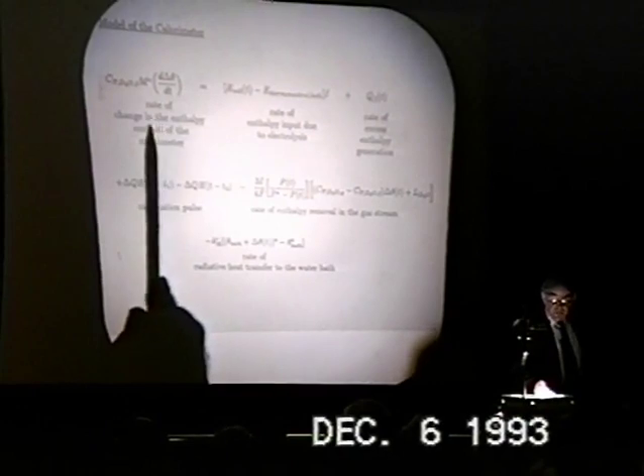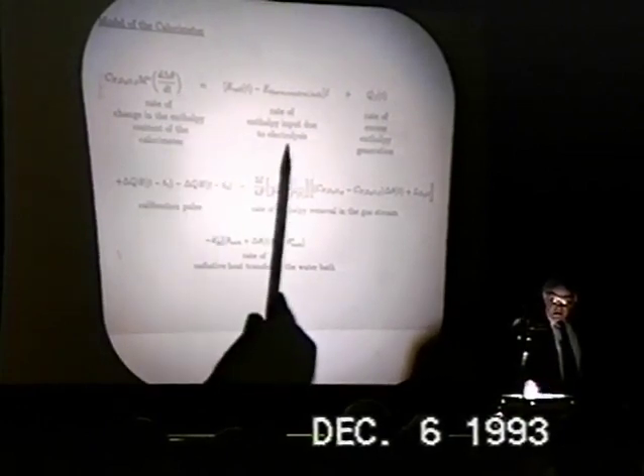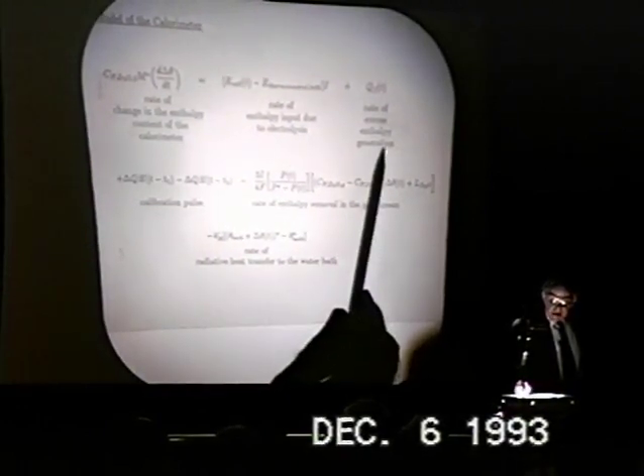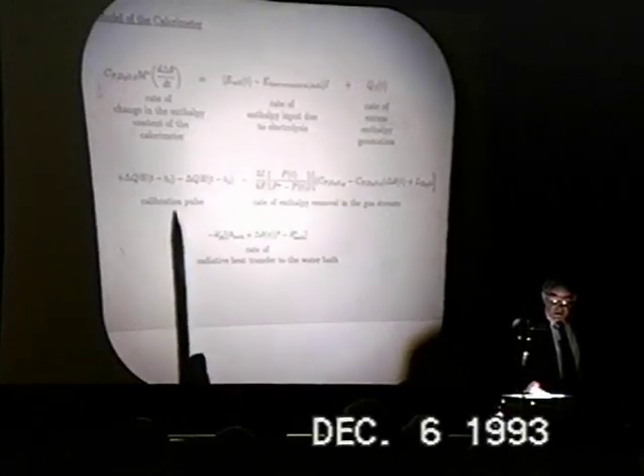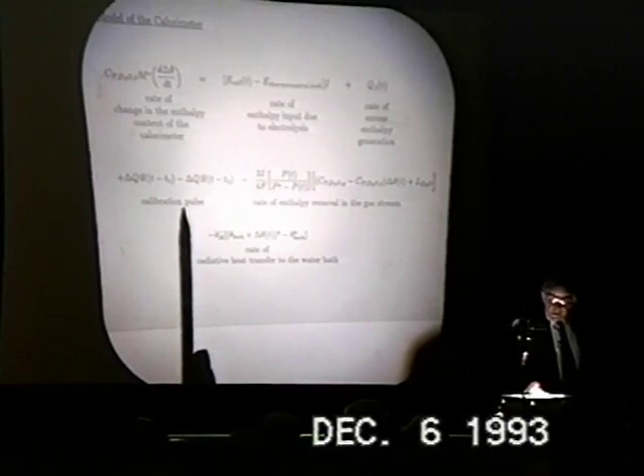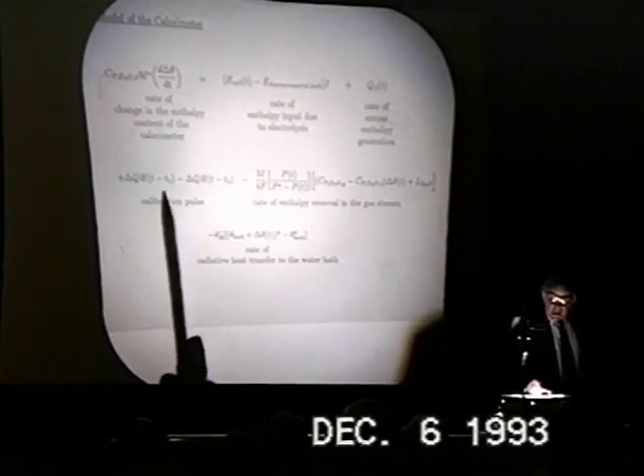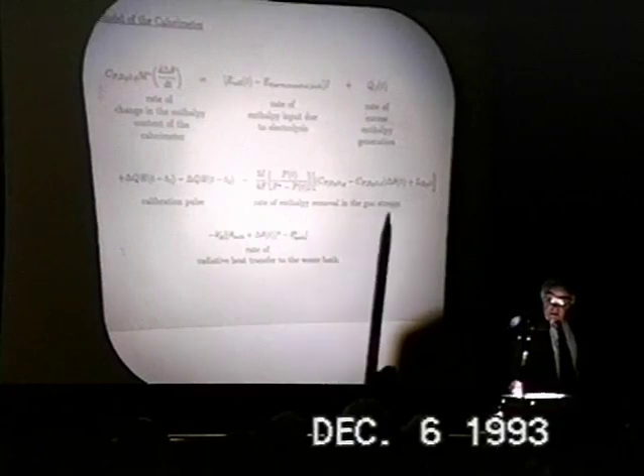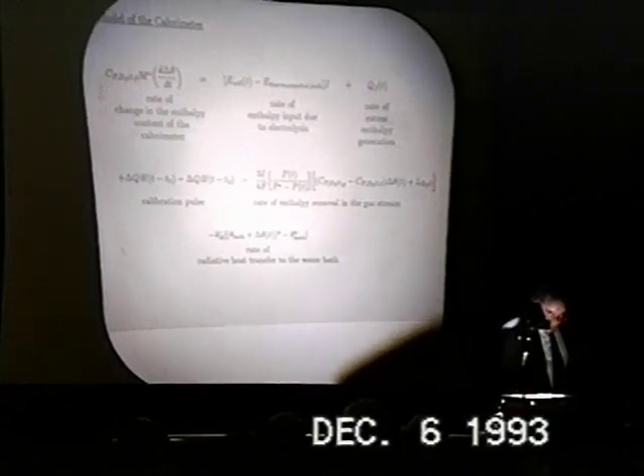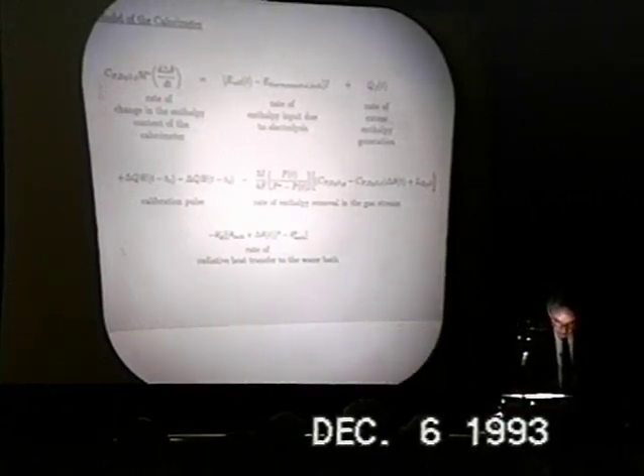This is the rate of change of enthalpy content of the calorimeter, enthalpy input due to electrolysis, excess enthalpy generation, calibration pulses. Notice the square pulses, not always, but mainly it's the square pulses. So this is a Heaviside step function. Here's the enthalpy removal by the gas stream, here's the radiative contribution, radiation to surroundings.